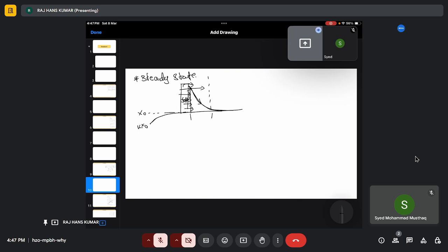Suppose the solid keeps on rejecting, and the speed with which the atoms are diffusing is not good, then this buildup will increase, right? And the part of the solid that's going to solidify will also get increased, right? To achieve this steady state, this is our assumption.